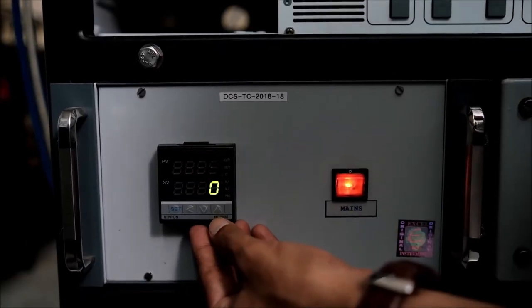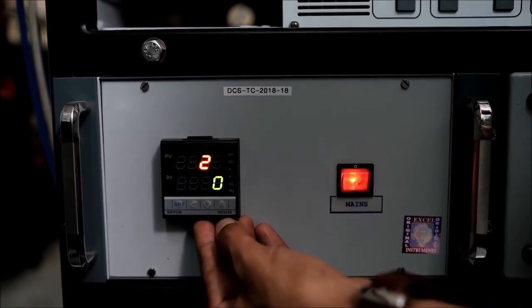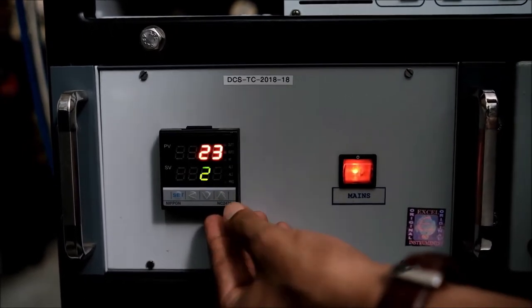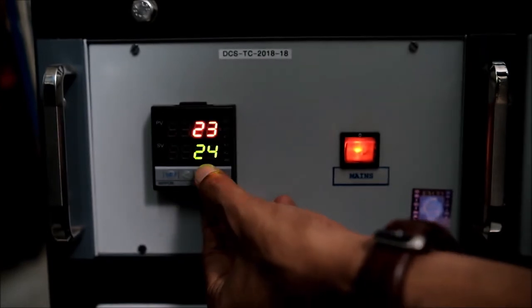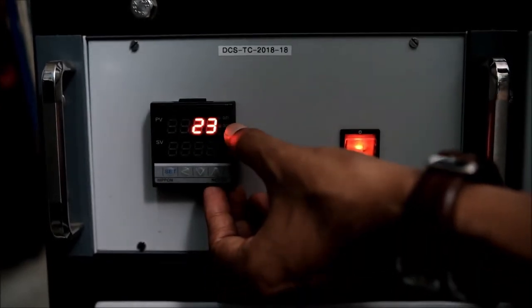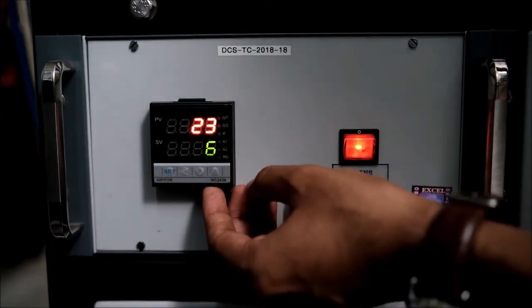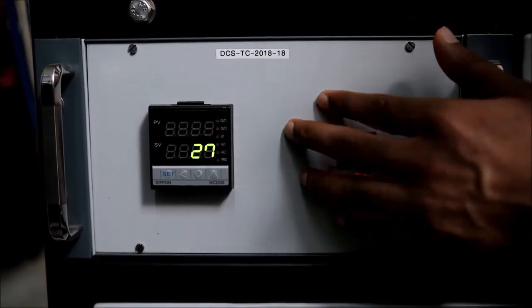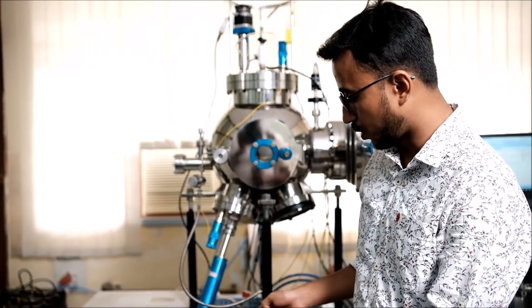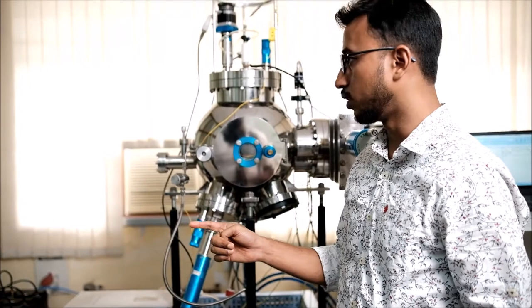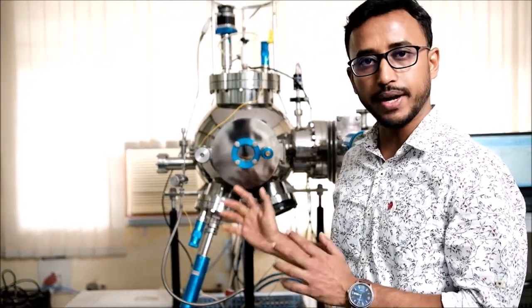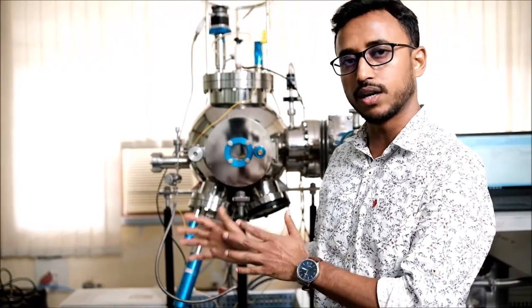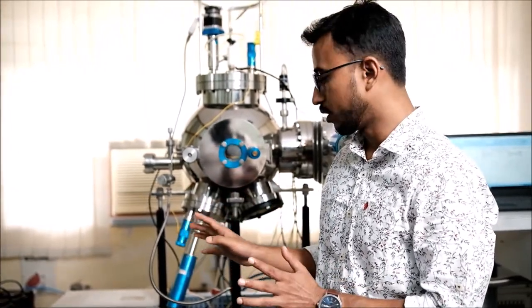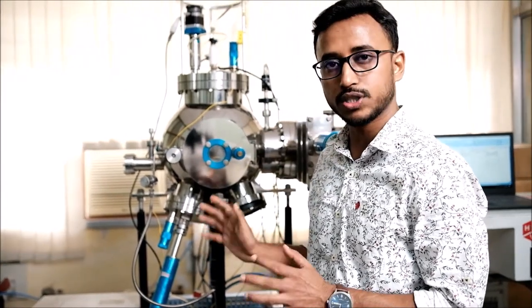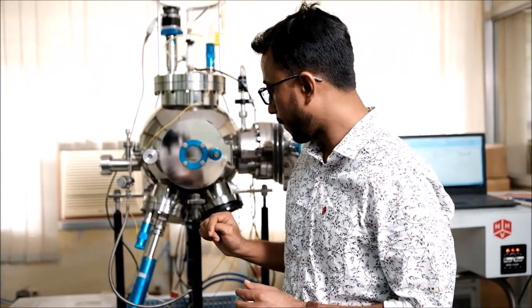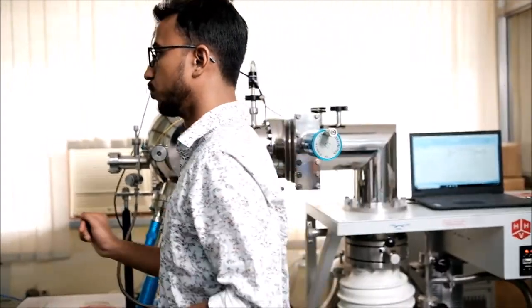Now as the program is set, I'll run the program. So I'll click and hold this up button. Yeah. So now the green light will show my set temperature, and the red light is the actual temperature at the substrate reading. So by the time the temperature reaches, I'll do the other processes. And before switching on the power, I will start the gas flow. So for my deposition, I want 90% argon flow and 10% oxygen flow. And I am using gallium oxide target material here. So I'll start the gas flow.